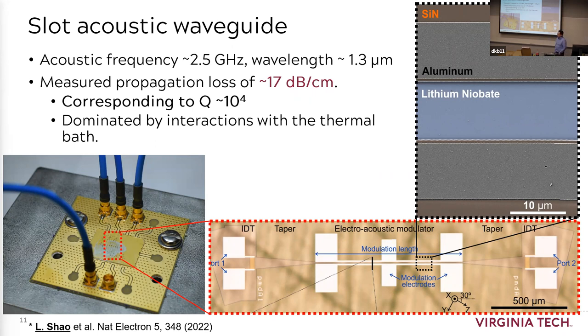This might be considered large, because if you go a centimeter, you may have only about 3% of the energy left. But if you consider the quality factor of this device, it's actually not too bad. It's like 10 to the 4. It's actually larger compared to a lot of mechanical devices and microwave components, like LC resonators. Usually they have Q factors of only 10, at maximum 100. So this is actually a high Q device.